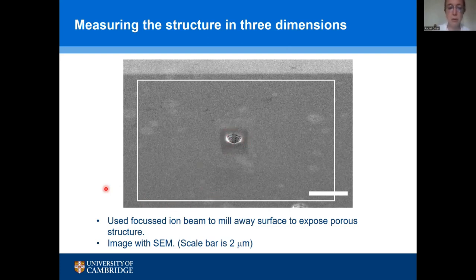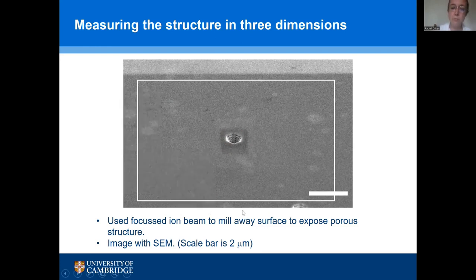And what I'm going to do now, I probably need to switch off my pointer for a second. When I run a video, what we're looking at here is an SEM image, a scanning electron microscopy image, but it's taken in a focused ion beam microscope. And when I run the video, I'm going to use the focused ion beam to scrape away the surface gallium nitride and see the porosity beneath. And then we'll scrape away the first porous layer and see a non-porous layer, and then scrape away again and see the next porous layer. And we can actually mill down through all these layers and reveal the structure that's formed.